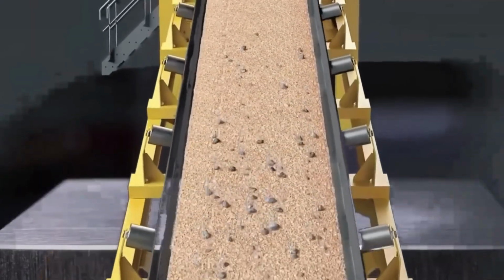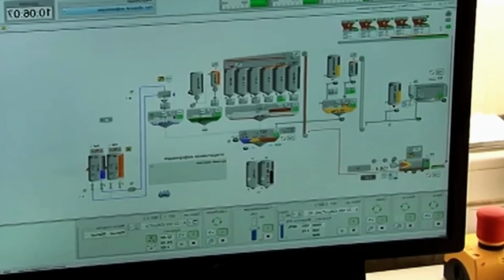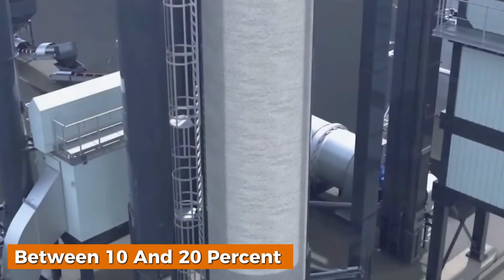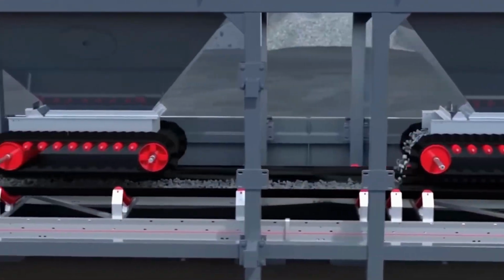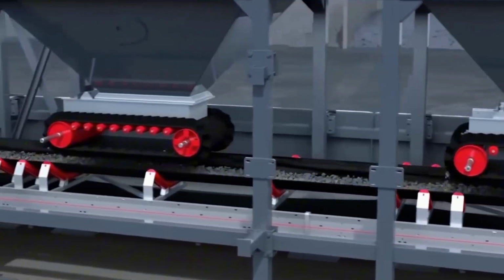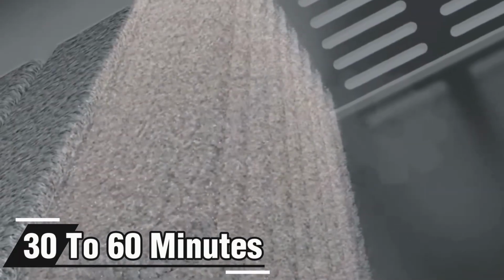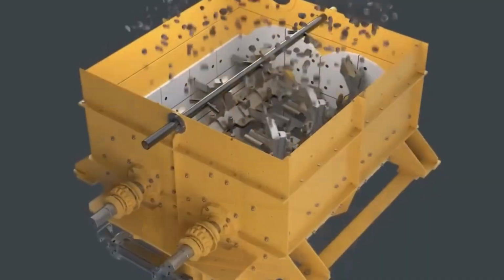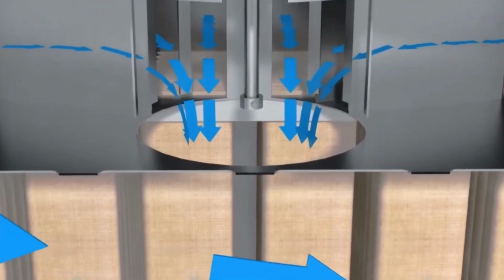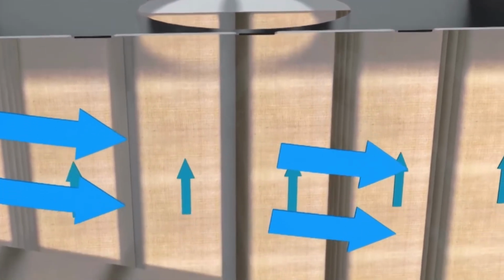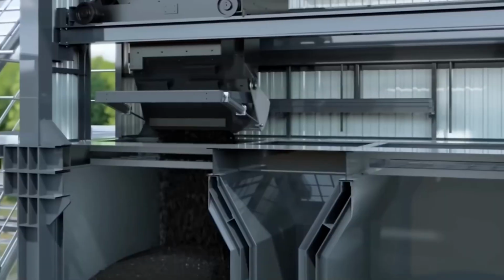Crumb rubber is introduced into the mixing chamber in carefully measured amounts, usually between 10 and 20% of total binder mass, depending on formulation requirements. Inside the mixer, heat-resistant paddles create a continuous vortex, forcing rubber and bitumen into sustained contact for 30 to 60 minutes. During this period, rubber particles swell as they absorb lighter oils from the bitumen. This increases mixture viscosity while greatly improving elasticity and resistance to cracking. These properties are critical for road surfaces exposed to heavy traffic loads and repeated temperature fluctuations.